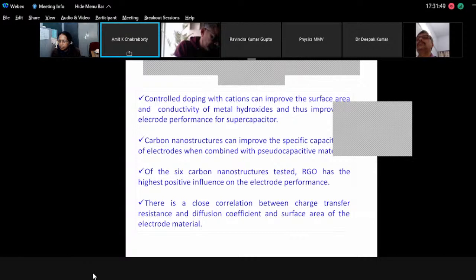We have shown this. Of the 6 carbon nanostructures we tested, RGO has given the highest positive influence on the electrode performance, and there is a close correlation between charge transfer resistance and diffusion coefficient and surface area of the electrode material for its performance.